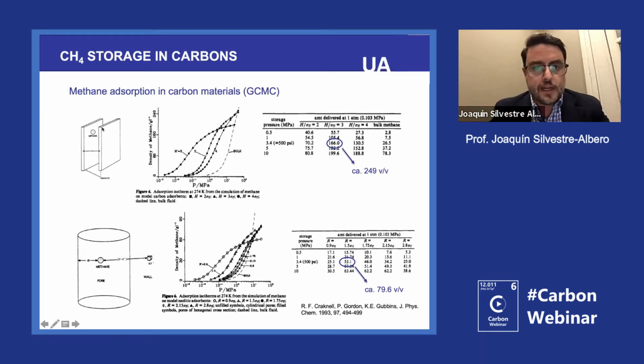So in the case of the carbon, what they were observing is that if you are working at low pressures, the higher density is in this type of pores where you can make 2 layers of methane. So we are talking about 0.8 nanometers. However, if we are thinking more about high pressure, as this is the case, you can see that the pores where you can allocate 3 or 4 layers of methane molecules have a higher density.